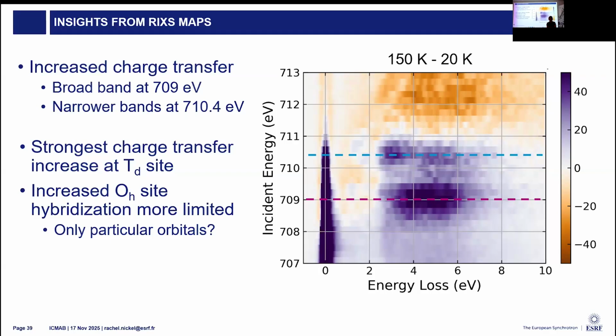Our beamline is slightly better in terms of the design of the spectrometer. So we have a special differential pumped shield on our sample space, which allows the continuous movement, so we don't have to stop the measurement and repump the vacuum. One of the downsides with working with soft X-rays is everything has to be measured in ultra high vacuum. So our beamline functionally is about 10 to the minus 8 to 10 to the minus 10 of millitorr of vacuum. If you have to stop and wait for pumping, it again eats into your experimental time.